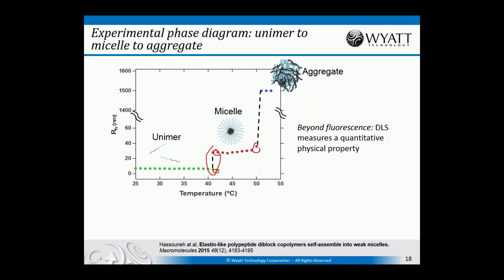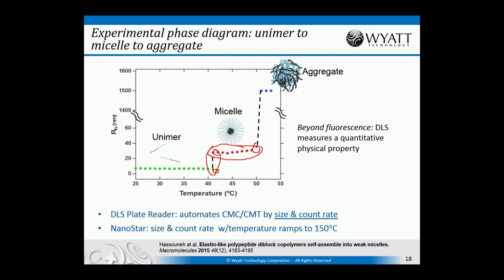Again, you typically might do this with fluorescence, but dynamic light scattering gives you a direct measurement, and you don't have to guess what the fluorescence actually means. It tells you what's going on. Dynamic light scattering tells you that there's a size change. These are the sizes, and then finally there's this transition to a much larger aggregate. This is a stable region for the micelle, and this is its actual size. So you get a really useful and direct indication of what your system is doing.